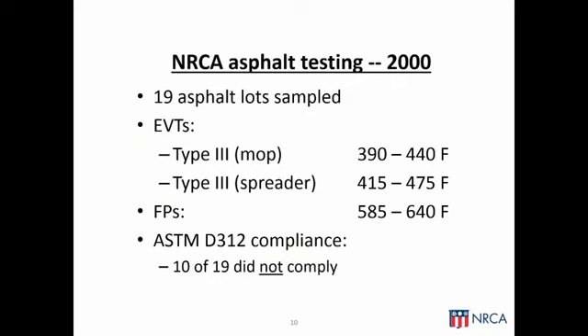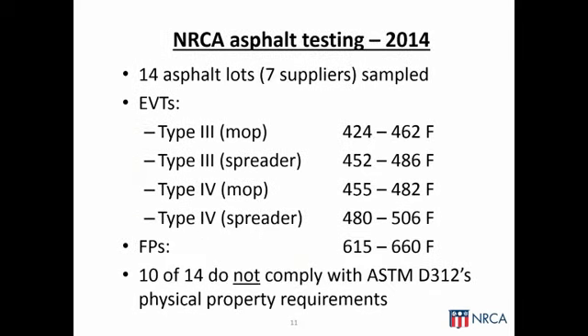And that was surprising to us because we were pretty comfortable prior to that that asphalt was in sync with the standard. This past year, we have repeated that testing, and we've tested 14 different lots of asphalt from 7 different suppliers from around the U.S., and the EVT values are in front of you on the screen, as well as the flash points. What I want to point out to you is the EVT values have crept up roughly about 35 degrees, in some cases a little bit higher than what we saw 12 years previous. And that was an interesting finding to us.